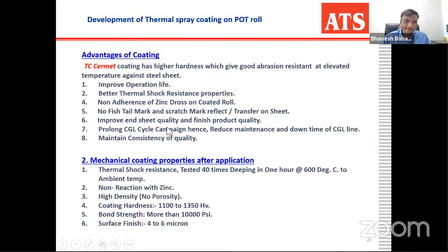If we see the mechanical coating properties after the application, thermal shock resistance was tested 40 times, dipping for 1 hour at 600 degrees Celsius and then to ambient temperature. So there is no effect, no problem in the coated surface, because we see the bath temperature near 450 in the galvanized line. It's non-reactive with the zinc, high density, so no porosity.